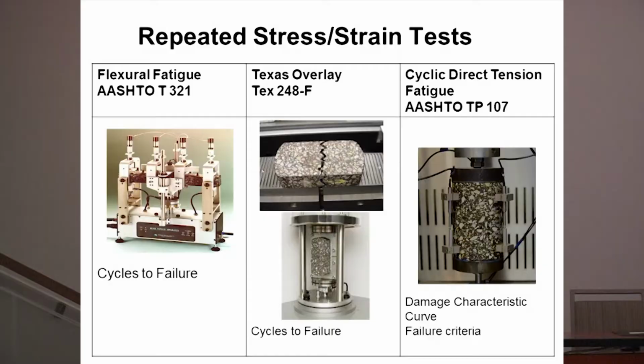So with respect to the repeated stress and repeated strain tests, the device over on the left, the flexural fatigue test, is the one that has been around for the longest time. This is work that was done by Professor Monismith starting back in the 1960s. What you have is a beam specimen that you repeatedly flex, and what you do is count the number of cycles to failure. And from that, you can generate a strain versus number of cycles to failure curve. It has a very difficult specimen geometry to produce, and very time-consuming testing, so it's not run very often.